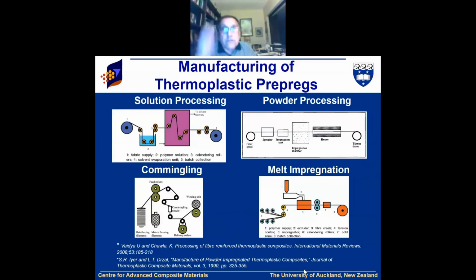Now, if you have continuous fibers, normally there are processes like solution processing, powder processing, commingling, melt impregnation. We were interested because solution processing, commingling, all of them have got some organic solvents involved, which are not very good, and people try to avoid. So we tried with powder processing, and we noticed that if you can control the parameters properly, then you can produce properties which are as good as those of solution processing. So we got that one.